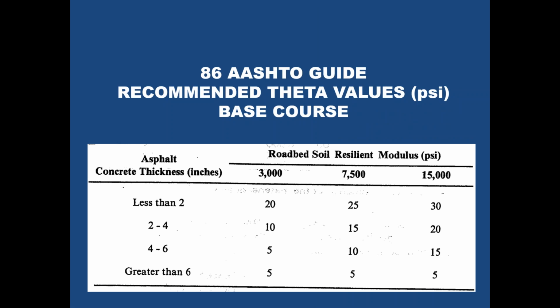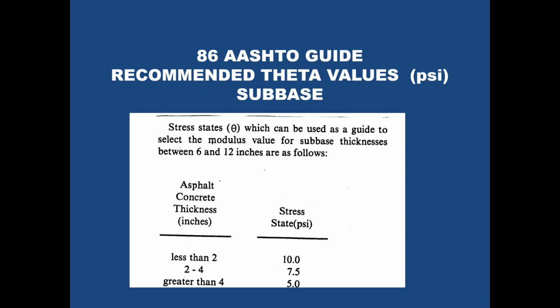Well, this showed up in the 86 guide for recommendations for that value. This is the modulus of the subgrade. This is the thickness of the hot mix, and that's the suggested value for the theta value. Okay, so if you get a theta, you know K1 theta to the K2, you can estimate what the modulus would be. Then if you want to do this for subbases, you're back to stress states, theta values that are quite low: 10, 7.5, and 5.